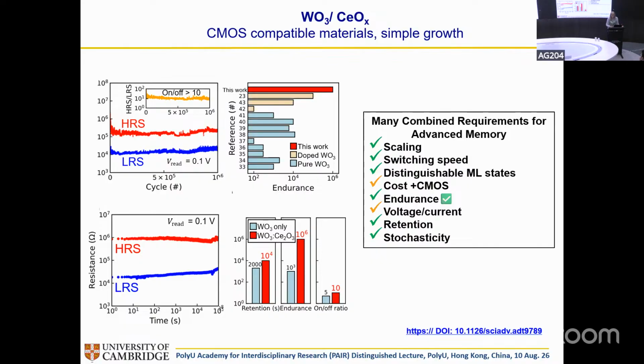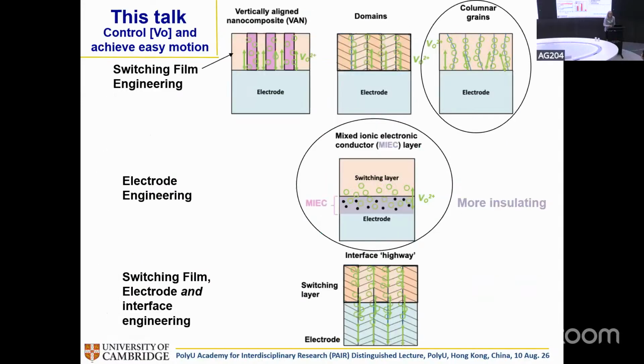So we've shown that the good part about this particular study here is you get very good endurance for tungsten oxide as an exemplar material by controlling the structure, basically. But let's move on a little bit now. We want to think about getting it even more compatible for industry. We want to make columnar grains. So we're going to grow grains of a columnar structured material.